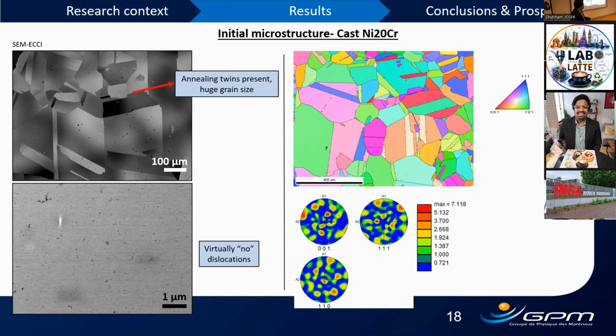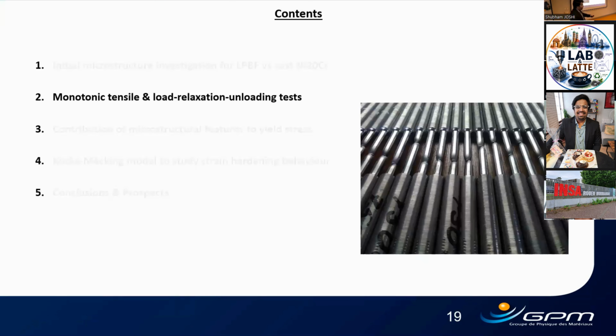The ECCI contrast shows us that the recrystallized sample looks almost dislocation free. Well, it has some dislocations, but the dislocation density is assumed to be quite small. So as of now, we can say that there exists a huge influence of the LPBF process on the microstructure of nickel 20 chromium. So certainly it might have an influence on mechanical properties. Let us look at the mechanical properties.